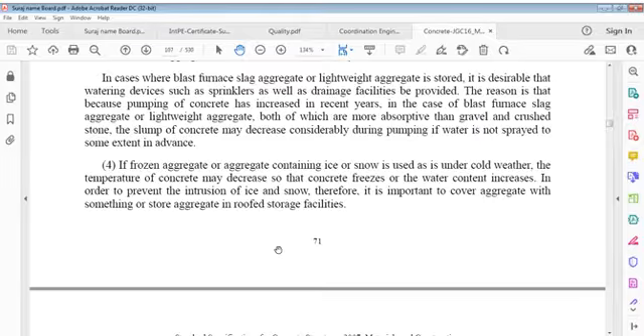So we say in cases where blast furnace slag aggregate or lightweight aggregate is stored, it is desirable that watering devices such as sprinklers as well as drainage facilities be provided. The reason is that because pumping of concrete has increased, blast furnace slag aggregate or lightweight aggregate are both more absorptive than gravel and crushed stone. Slump of concrete may decrease considerably during pumping if water is not sprayed to some extent in advance.